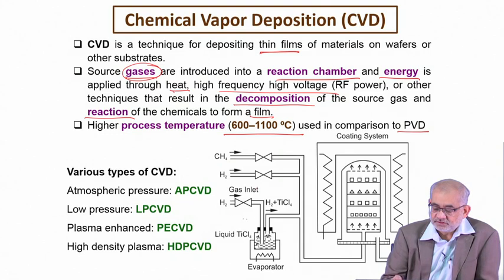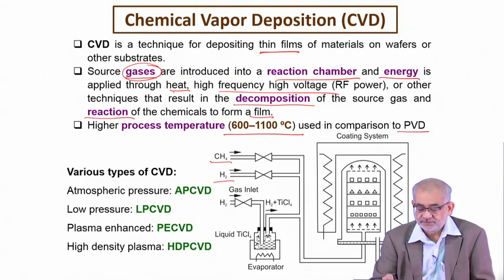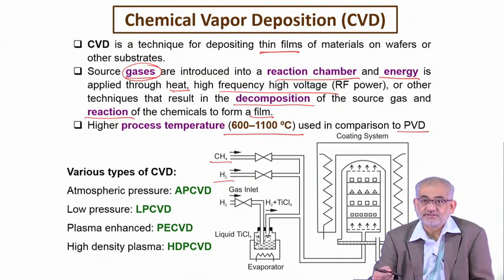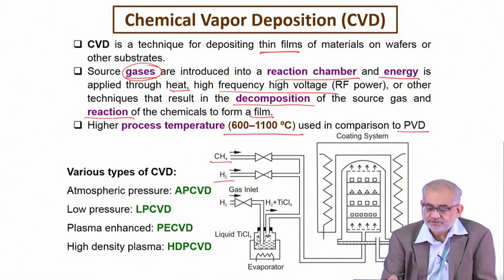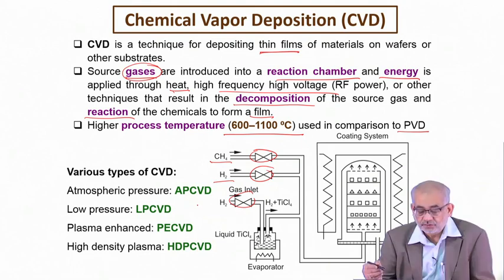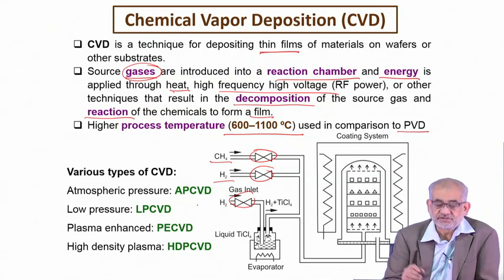This is where CVD differs from PVD — normally in case of PVD you would not go beyond 400–450°C, which is typically to take the material of high vapour pressure into the vapour state. You can produce a compound layer and feed in different kinds of gaseous mixtures — like a hydrocarbon and hydrogen together, or titanium tetrachloride and hydrogen together. The substrate remains inside the chamber, and the temperature, pressure conditions, and gas mixture can all be varied. You can close or control any of the valves to control the flow rate, or close one particular gas for a period of time to produce a film that is compositionally different from another film. So the reactions can be varied and hence the composition of the films can be changed.